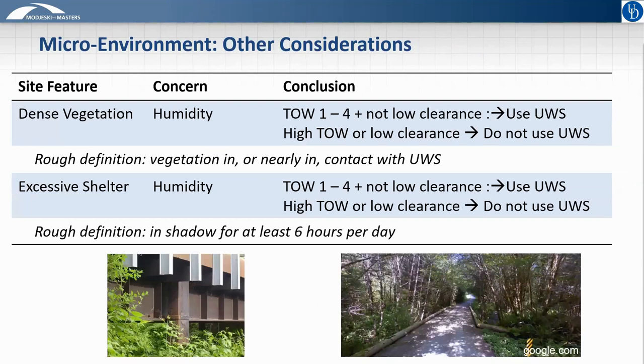In addition to what the bridge is crossing, 2 other microclimates to consider are those with dense vegetation and excessive shelter. Dense vegetation can be roughly defined as the vegetation being in contact or nearly in contact with the structure, as this increases the humidity or traps moisture, as shown in the photo on the left, where this girder is experiencing some through thickness section loss in that location. Dense vegetation, like shown on the right, can also cause excessive shelter, which has been roughly defined in some international guidelines as the bridge being in shadow between 9 a.m. and 3 p.m., which we loosely translated to be in shadow for 6 hours per day. In either of these situations, options are to modify the site if possible or to modify the structure.